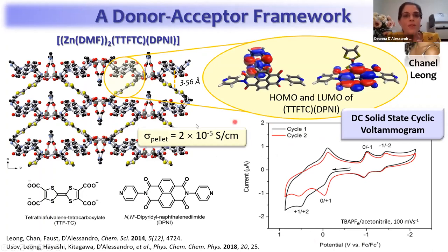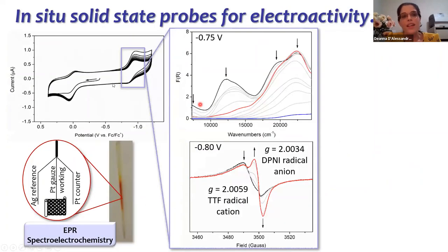And if we now use our solid state spectroelectrochemical methods, what we see is that we can reversibly cycle between the +1 and -1 states. If we try to move outside of this electrochemical window, then the whole material degrades. But what we do see in the UV-vis near infrared spectroelectrochemistry is a charge transfer band, which you see here in the middle of the visible.